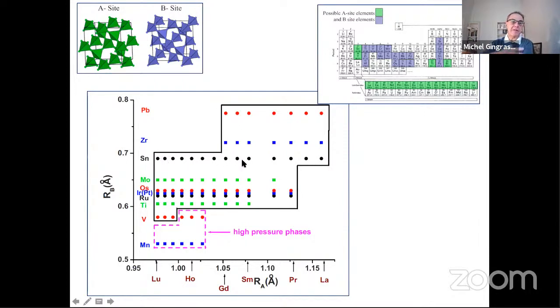And so the stannates are very interesting. All the rare earth pyrochlores can be realized. But if you go, for example, to titanium, then you can only realize the heavy rare earths, because by the time you get to samarium here, the stability ends. For example, praseodymium titanate is not a pyrochlore structure. It's a distorted fluorite-type structure. And so these are the constraints of the materials that can be synthesized, where depending on what ion sits on the transition metal site, you can have access to different lanthanides or rare earths. This understanding of what's possible in terms of the rare earths was figured out in the late 1980s and early 1990s.